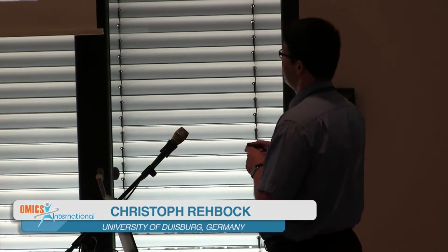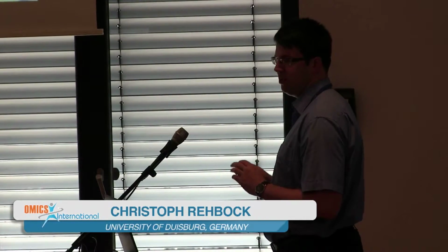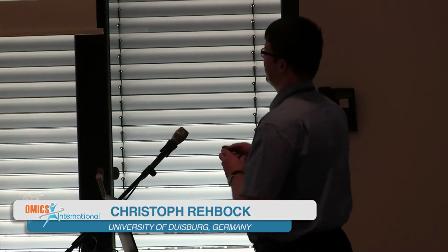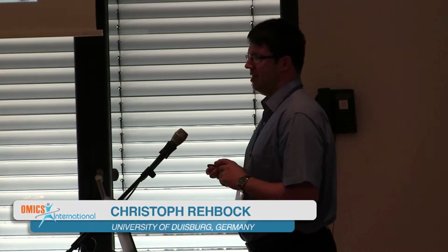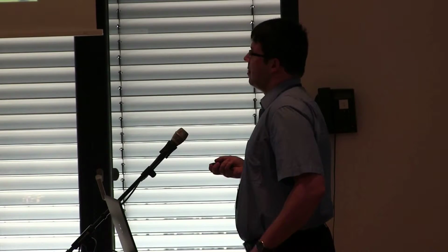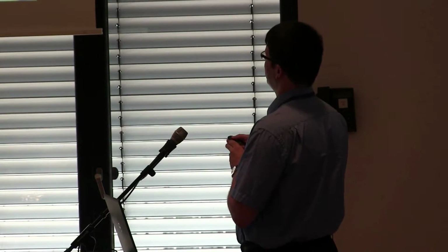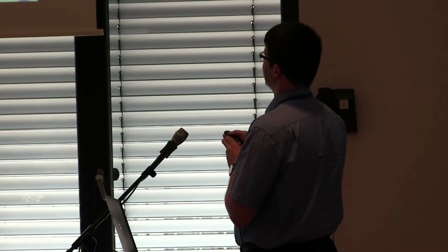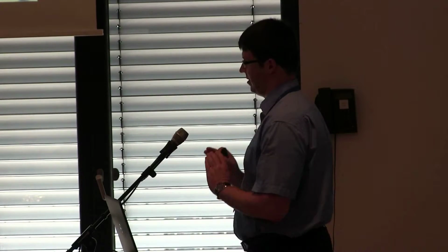Okay, now we switch to the part where we observed some toxic effect, which was for the silver and the silver-rich alloys. The silver, I will not go into detail here because it's well known that silver nanoparticles and also silver ions are known to influence biological systems, but I want to go to the silver-rich alloy because I want to point out that there's a steep drop from 50-50 to 20-80. So here we have a steep increase in the toxicity. The question is why does this happen, and does this also occur in other biological systems?